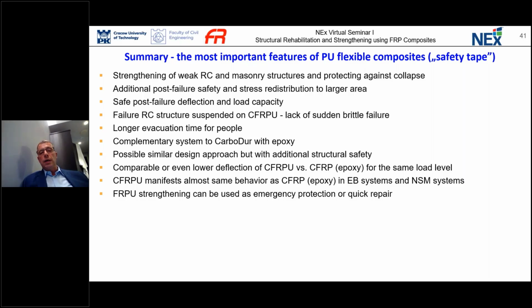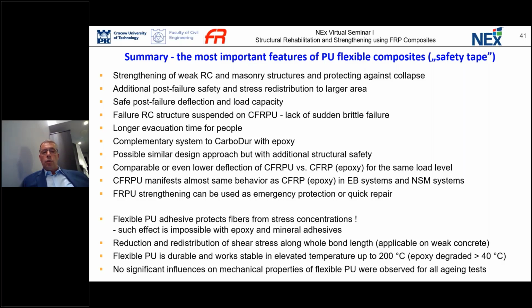FRPU systems also can be used as emergency protection or quick repair, because it cures very fast, in 10 hours, when we did repair on a shaking table and tested the system. So also, this kind of polyurethane reduces the stress concentration, so it protects the composite material. And it is very unique because you cannot obtain such an effect using stiff epoxy resin or stiff mineral adhesives. And reduction and redistribution of shear stress along the whole length help in protection of weak concrete structures when the substrate is weak, because in this case we do not generate the high stress peak that is responsible for damage